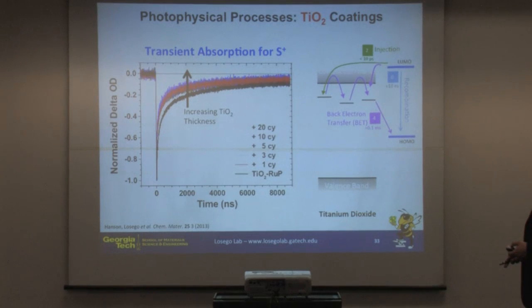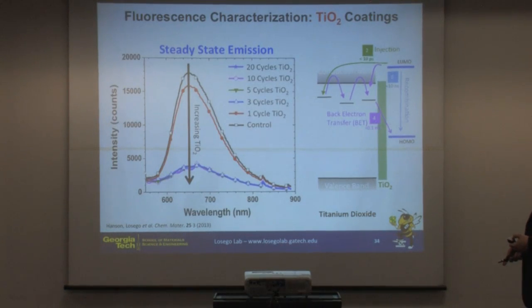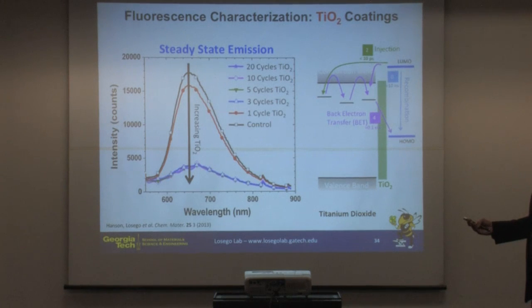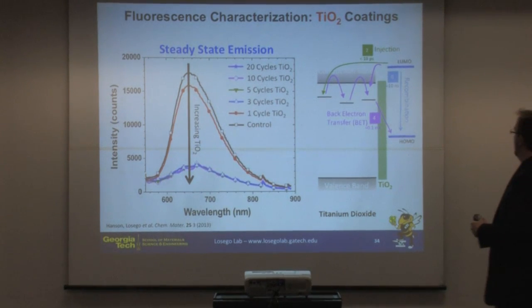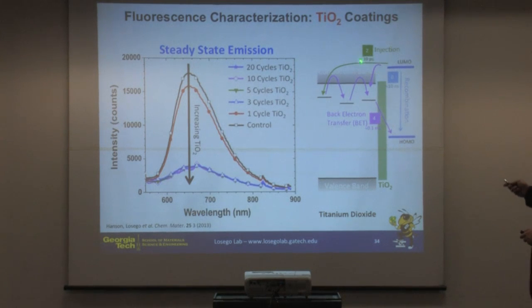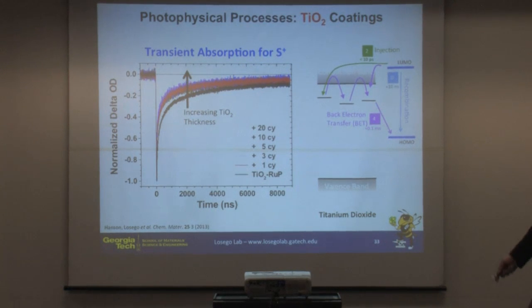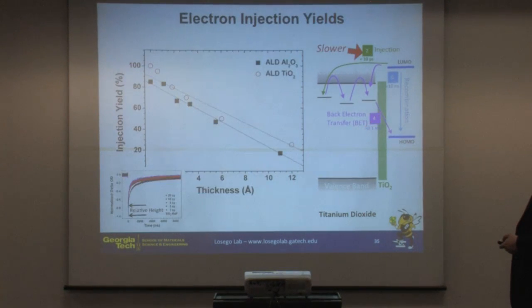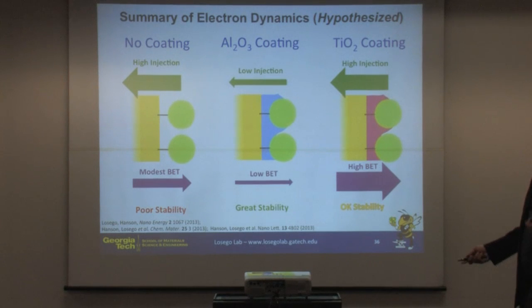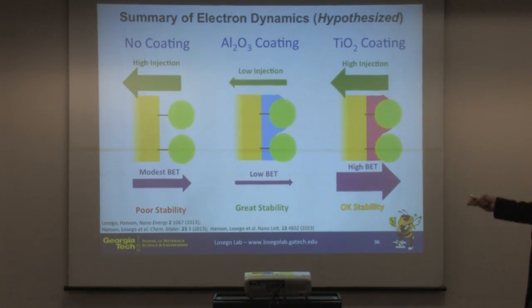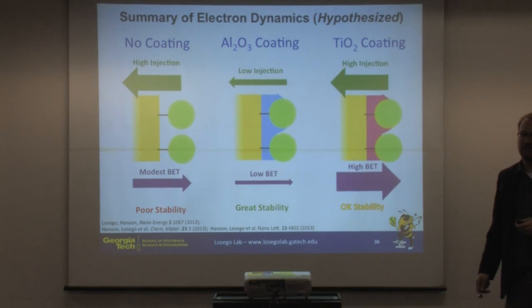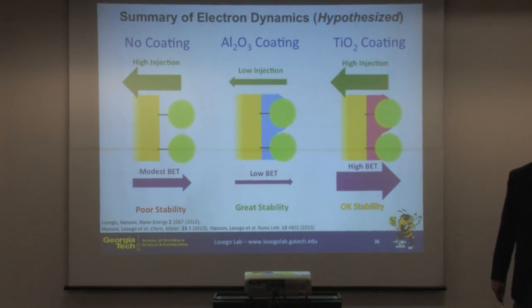And so we have a number of other measurements. With TiO2, we actually don't see much of a change. And we see some interesting things in the fluorescence, which tells us about this recombination process. And so we've interpreted some of this. We've not measured this directly. This is the thing that we're working with Tim on now because we need to get to picosecond measurements. These are all nanosecond measurements, these transient absorption measurements. So we needed a faster measurement system to probe that directly. I've summarized it all here in one slide to make it very simple and not go into all the details, but I'm happy to discuss more, and we have some publications on that.